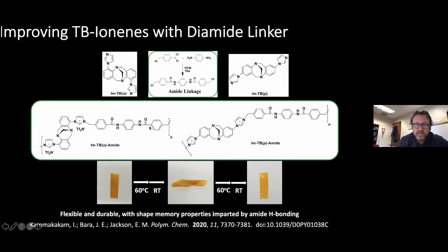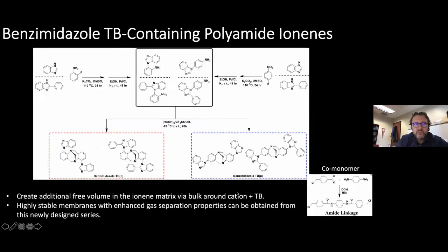And we think that's because of the hydrogen bonding that's happening, as well as the ionic charges. There's quite a bit of force holding that material together. So if we can deform it, we can actually heat it and cause it to go back to its original shape. So that was very exciting, and there'll be more about that later.